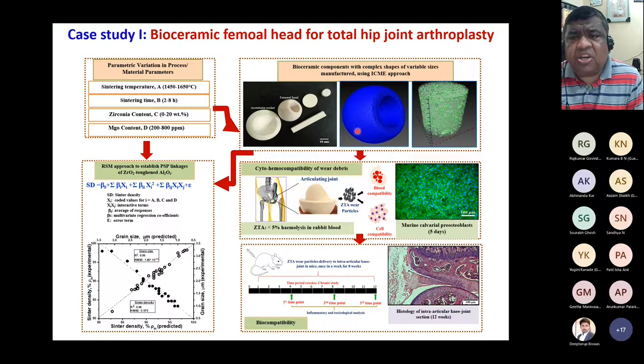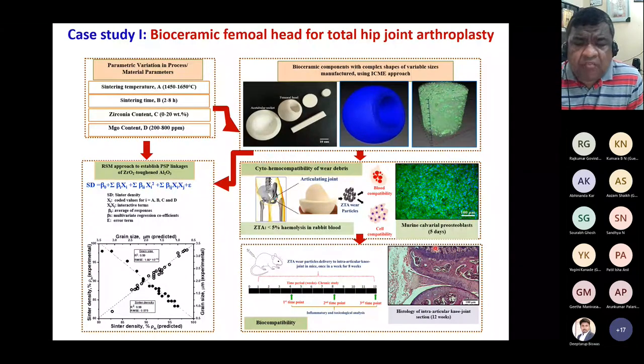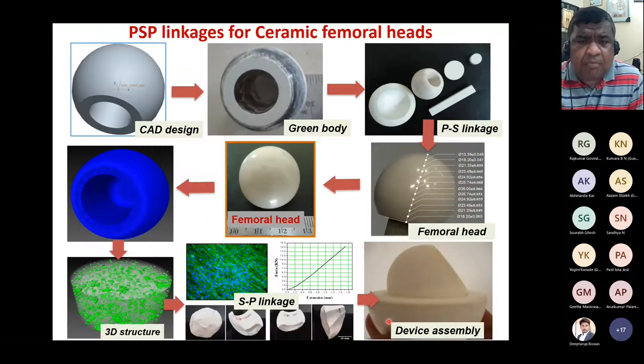And if you look at the three-dimensional microstructure, which is obtained using microcomputer tomography analysis, you would notice that there is a very good distribution of the zirconia particles as a second phase in the alumina matrix. These materials have also exhibited very good biocompatibility, both in the animal model and also hemocompatibility with the rabbit blood, particularly less than 5% hemolysis, which we have recorded in the rabbit blood.